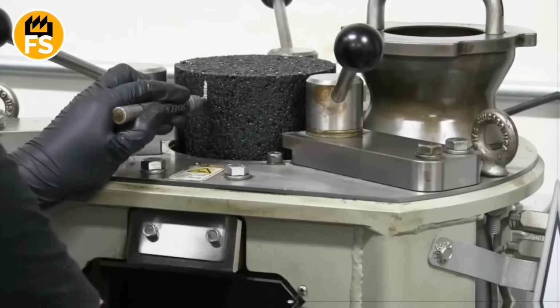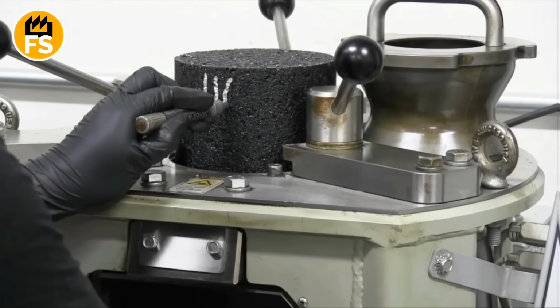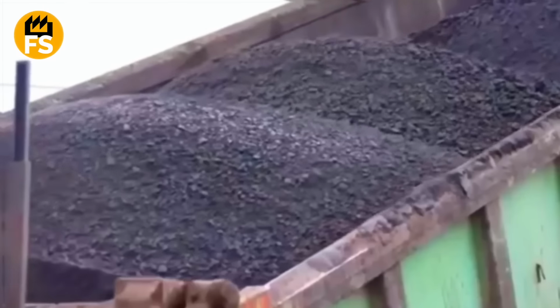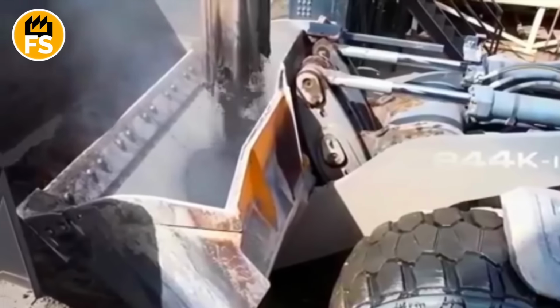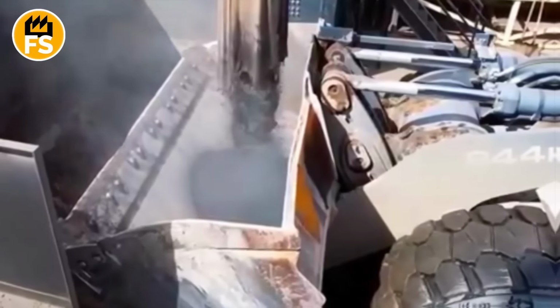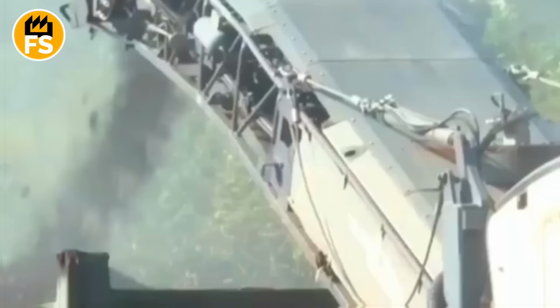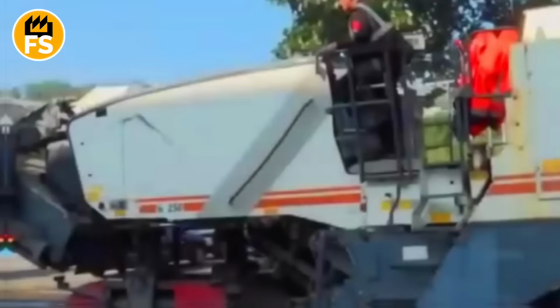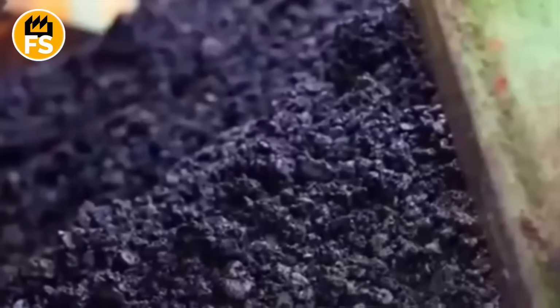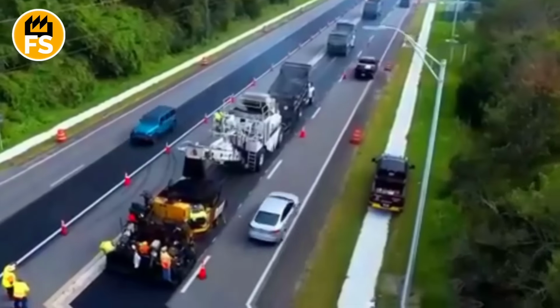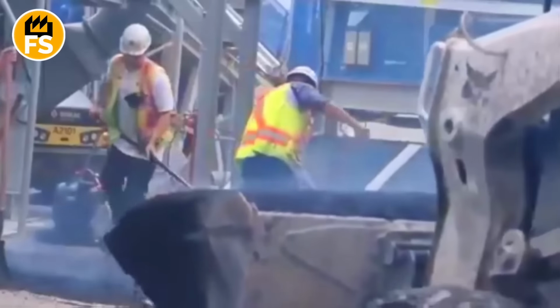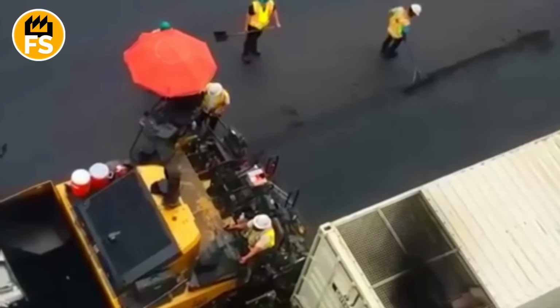That's exactly why engineers had to find a solution that would allow asphalt to maintain its shape even under extreme heating conditions. They replaced regular bitumen with modified bitumen, with polymer additives that change its physical properties. Such bitumen holds its shape at temperatures up to 176 degrees Fahrenheit. This means even when the road surface heats up to maximum levels, the material still remains stable, doesn't flow, and doesn't change structure.